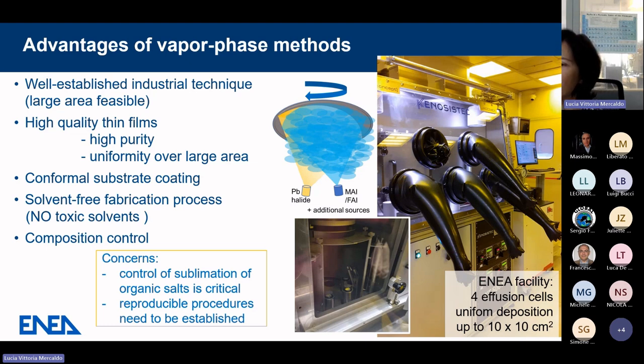Here in the figure, I'm showing our facility in ENEA. We have an evaporation system with 4 effusion cells that allows for uniform deposition up to 10 by 10 centimeters square. This is integrated into a glove box. And this glove box is in line with all the other glove boxes that I've shown in the other pictures before, so that also for completing the full solar cells, one can keep the samples always in controlled atmosphere.